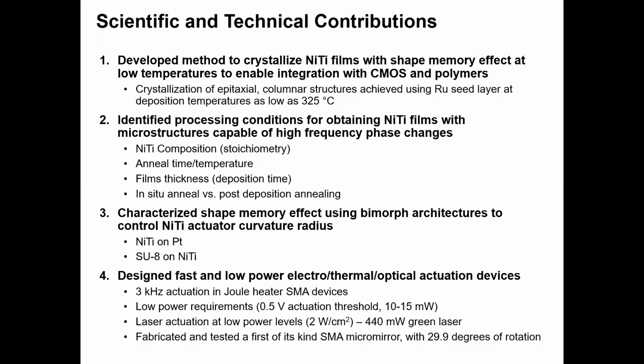The third contribution deals with building and characterizing shape memory effects using bimorph architectures to control the NiTi actuator curvature radius and degree of unfolding. And this was primarily done using either NiTi on platinum and SU8 on NiTi actuators at the MEMS scale. So in each case, analytical modeling supplemented by experimental characterizations help to confirm or determine the bending radius in the bilayer stacks. And the fourth and final contribution deals with fast and low power actuation of SMA bilayers, where the SMA actuation frequency was shown for the first time to reach 3 kilohertz at reversible actuation speeds, also requiring low voltage actuations, and finally a preliminary demonstration of a first of its kind SMA micromirror with large deflections.